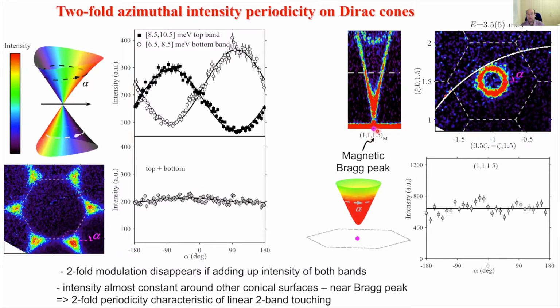This is the experimental data. That's the Bragg peak. That's the dispersion relation. If we take a constant energy contour here, you see the intensity is uniform everywhere around here. So if we plot the intensity as a function of angle, we get a constant. So the fact that the intensity is very strongly modulated with angle, moving around the nodal point, is really a characteristic of linear band touching of these two bands. It's a fundamental property of the topological aspect of this linear touching point.